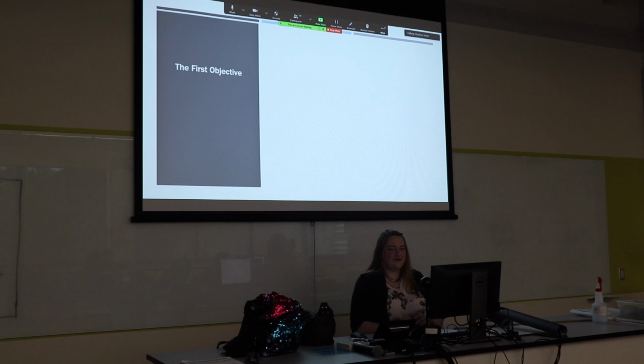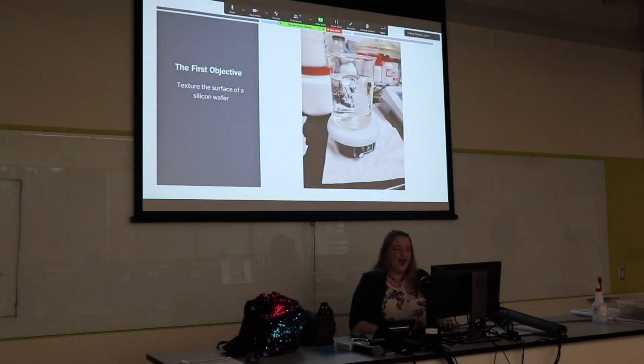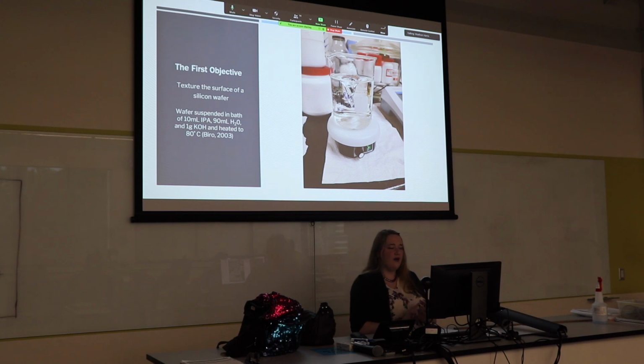So our first objective for this cell was to texture the silicon. So we created a bath that was alcohol, water, and potassium hydroxide, heated it to 80 degrees Celsius, and just suspended our sample inside of it for about 30 minutes.